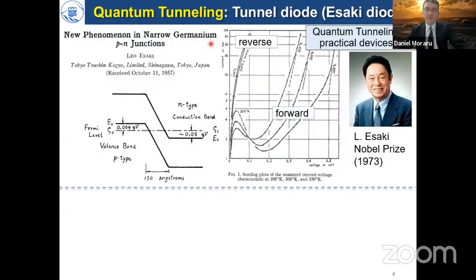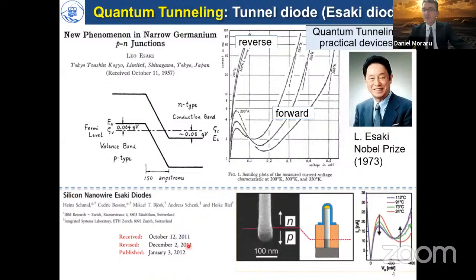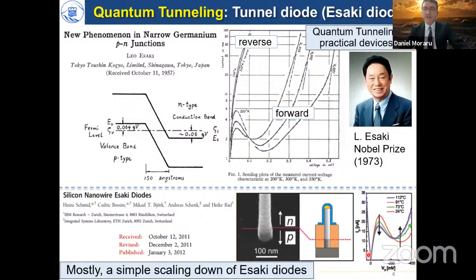What happened in the meantime was that about 10 years ago, we get the first reports of silicon nanowire Esaki diodes. And they used CVD technique to create vertical NP wires. And what was observed in these devices was basically the telltale signatures of Esaki diodes: the negative differential conductance peak in forward bias and the high reverse bias current. It's very nice. We can enter the world of nanoelectronics with these devices, but generally, this gives us a simple scaling down of Esaki diodes.